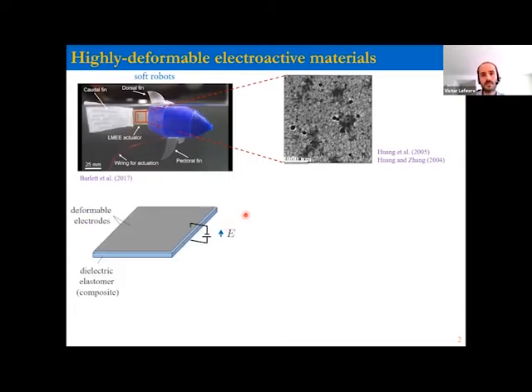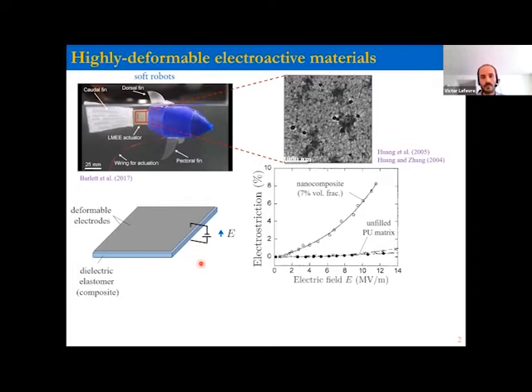So this is a schematic of a typical setup that people use to probe the mechanics and the electrical behavior of these materials. They take a thin film of the material, being either an elastomer or a composite, and they apply a voltage through the thickness of the film, and they measure how much the film deforms. And this deformation, this strain, is the so-called electrostriction.